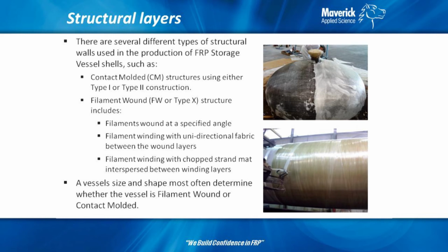Filament winding is stronger and typically will be thinner because of that strength, but the corrosion resistance of that structural layer isn't nearly as much because, again, 80% of the structural package in the winding band is glass. So there's only 20% resin in that package. So it's not nearly as chemically resistant as a structure built contact molded.